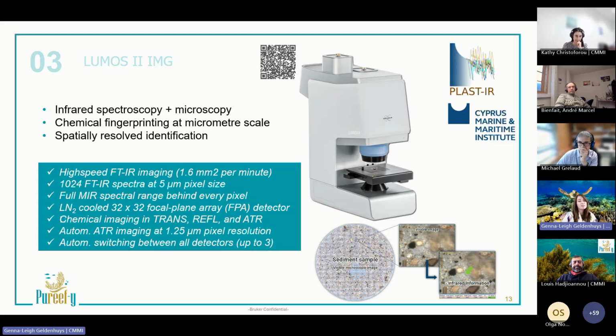Some of the capabilities do include high-speed imaging, 1.6 millimeters squared per minute, over 1,000 FTIR spectra at 5 micrometer pixel size, full mid-infrared spectral range behind every single pixel. It does have a liquid nitrogen-cooled focal plane array detector. Chemical imaging is possible in transmission, reflection, and ATR, and there's also automatic switching between all detectors.